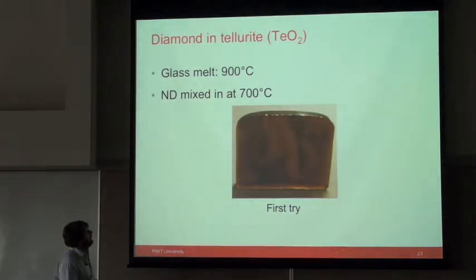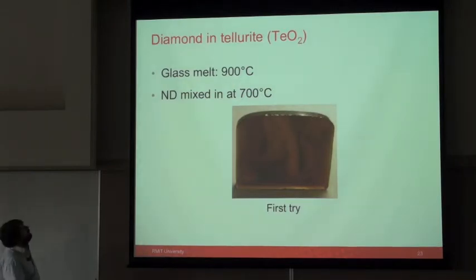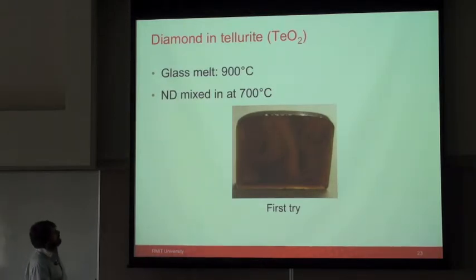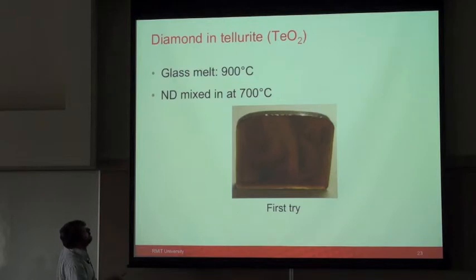And so we started our collaboration with the University of Adelaide, and their favourite soft glass is something called tellurite. So tellurite is tellurium dioxide here. You can make this glass at 900 degrees centigrade, and we can put the nanodiamonds in. So we make the glass here, but then the nanodiamond is incorporated at a slightly lower temperature. This is our first billet, and this is really quite an exciting result. I know it doesn't look like very much, but these swirls in here are nanodiamonds.